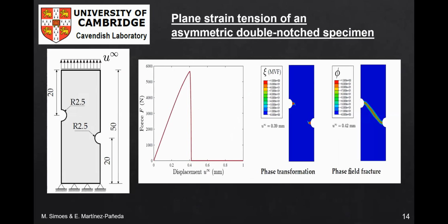An asymmetrically notched plane strain bar is investigated here to model mixed mode fracture and crack coalescence. The results are shown in the right. Contrary to the response observed in the previous slide of the square plate, a sharp drop in the force versus displacement curve is observed, which is indicative of brittle fracture with little inelastic dissipation. The inelastic region is confined to a small area in the close vicinity of the tips of the notches. No inelastic or shear bands are observed, such that as soon as cracking initiates at the notch tips, the cracks coalesce and unstable cracking is observed.